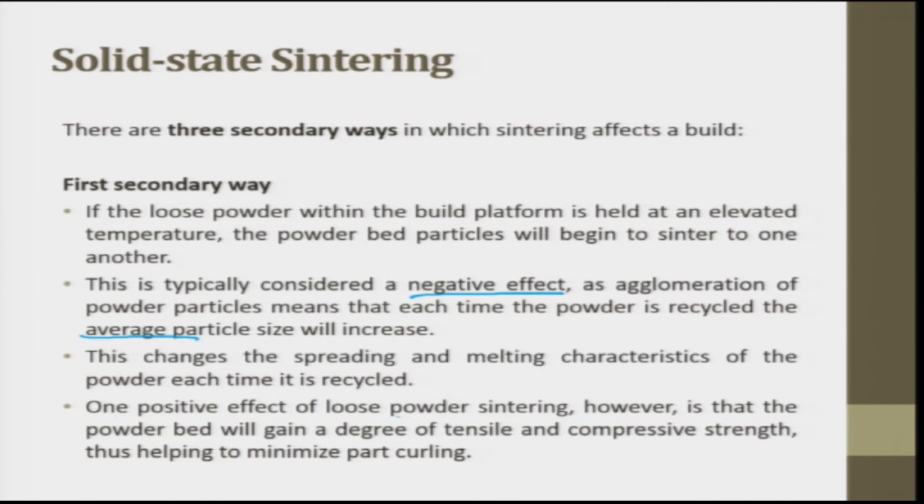This changes the spreading and melting characteristics of the powder each time it is recycled. One positive effect of loose powder sintering, however, is that the powder bed will gain a degree of tensile and compressive strength, thus helping to minimize part curling. Okay. So when there is pre-sintering happening, you also have an advantage: curling will not be there.